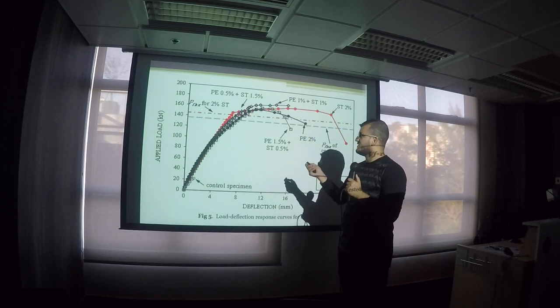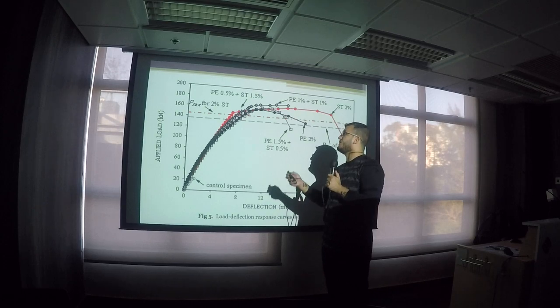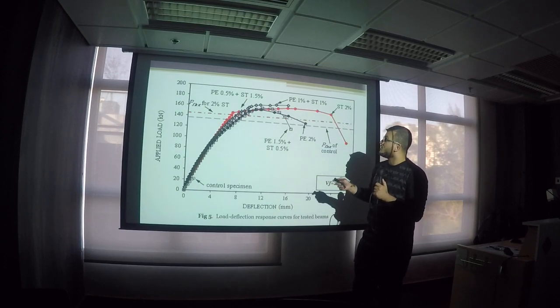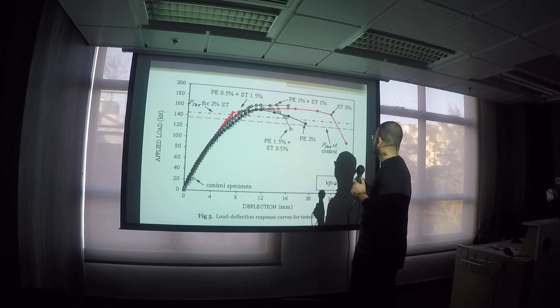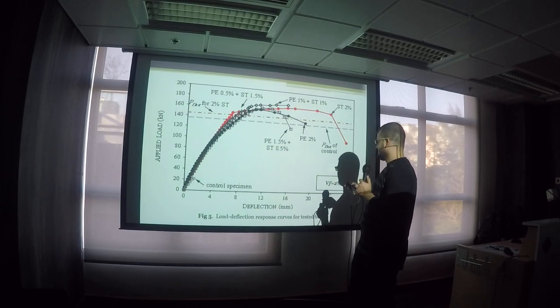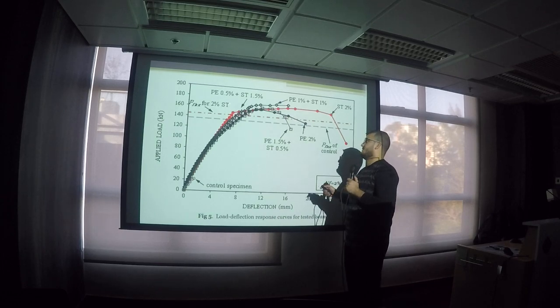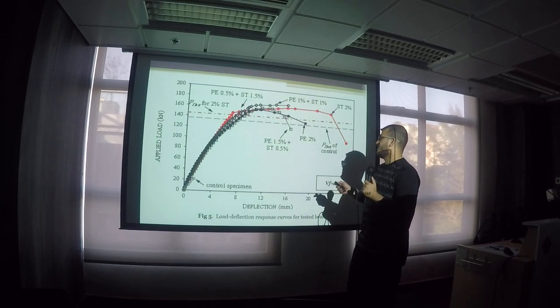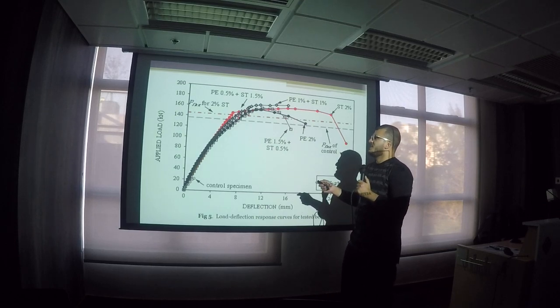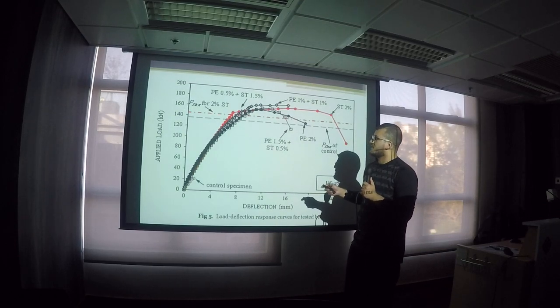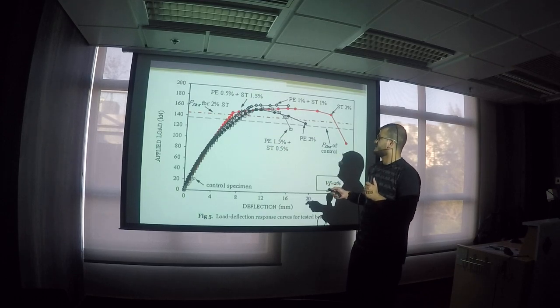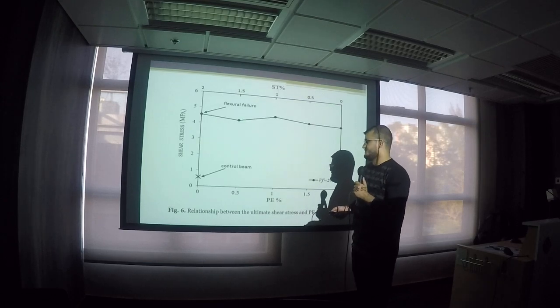Why is that? Because the steel fiber has a higher modulus of elasticity compared to the polyethylene one. We have also noticed that all the beams have an extended yielding plateau, and some of them already failed in shear, so they have large bilinear strain hardening. Again, we have calculated the theoretical flexural strength of the beams, as you can see here. This is the theoretical flexural strength of the control beam, and this is the theoretical flexural strength for the 2% steel beam. All of the hybrid beams have exceeded this theoretical strength, as you can see here.